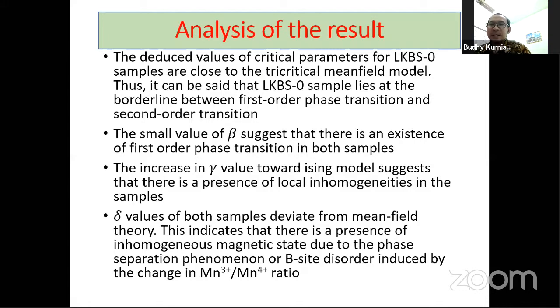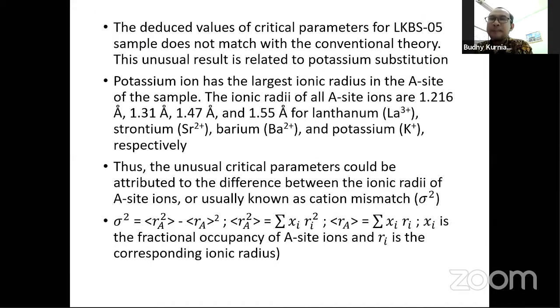And from the delta value, there is a presence of inhomogeneous magnetic state due to phase separation phenomenon or disorder induced by the change in manganese 3+ ion and manganese 4+ ion ratio.